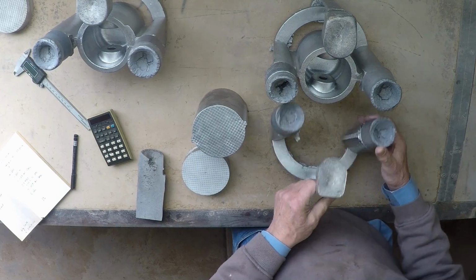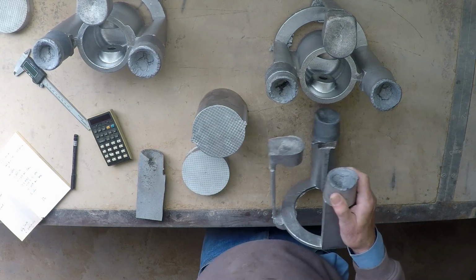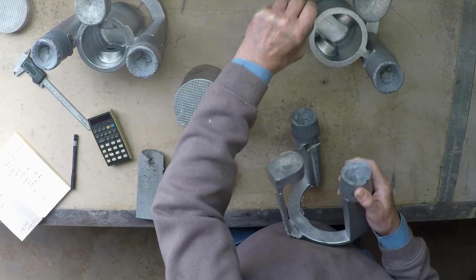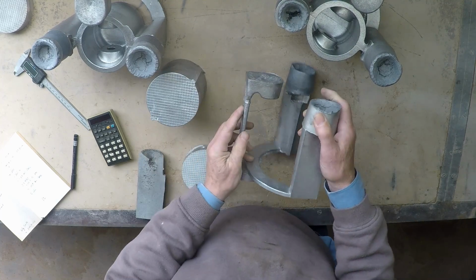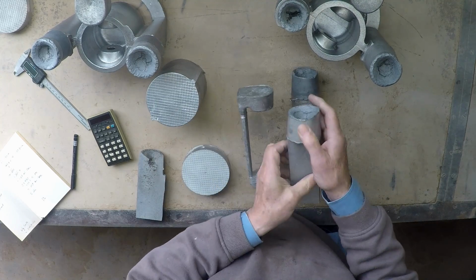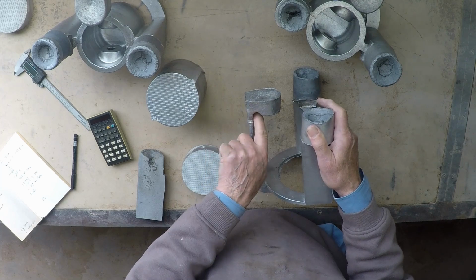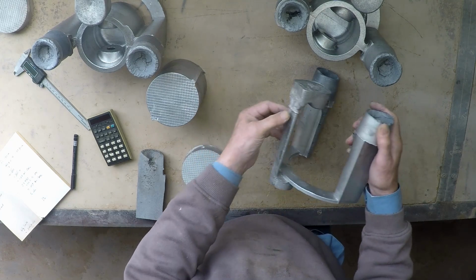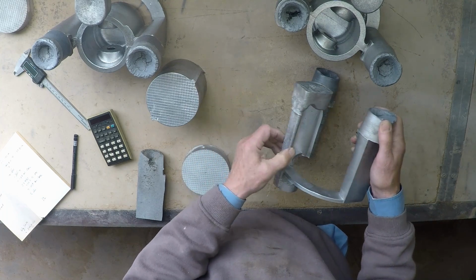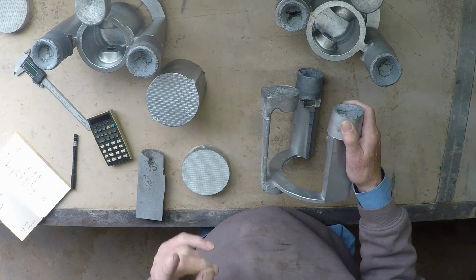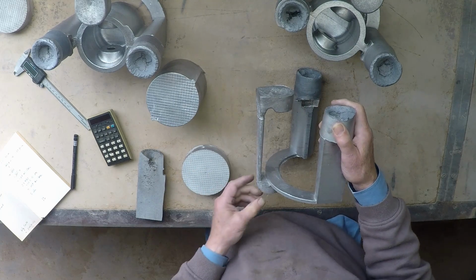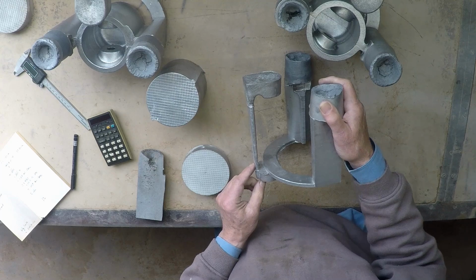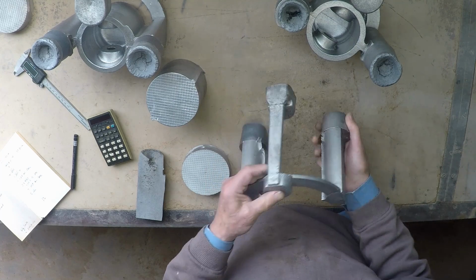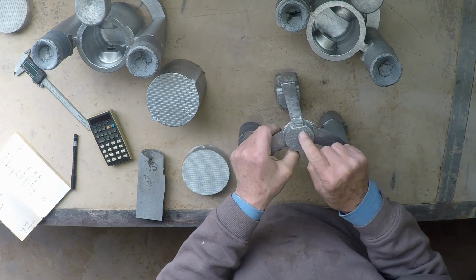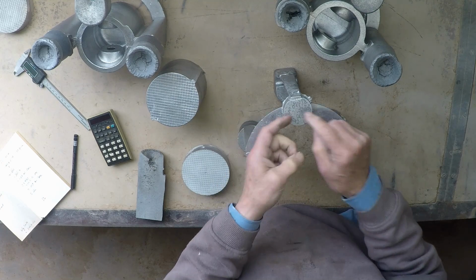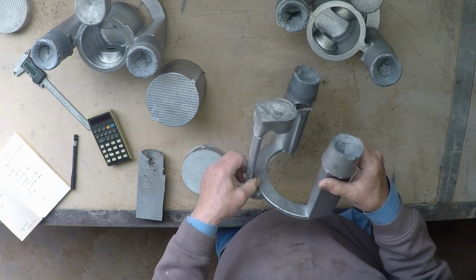Now, we decided to do this with what we believe to be the best sort of gating system possible. We have here a decent pouring basin with a ridge, a tapered sprue. It's a slot sprue in this case. We chose a slot because that gives increased friction and will help slow the metal down more. Secondly, it also mates well with the filter that we put in the bottom of the mould, which you can see now sitting here in the metal.